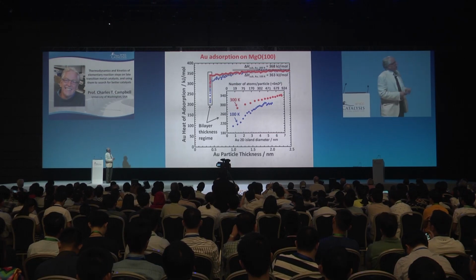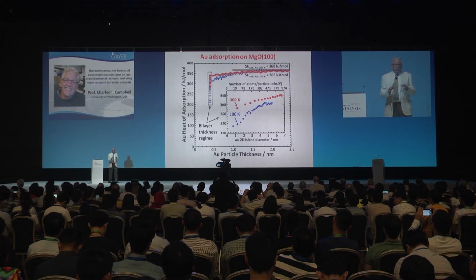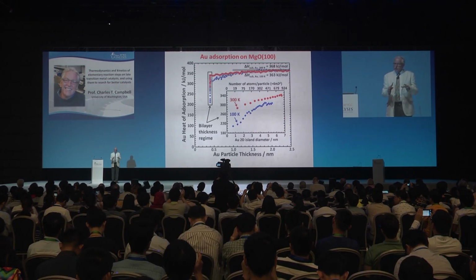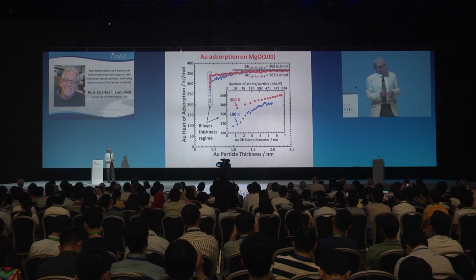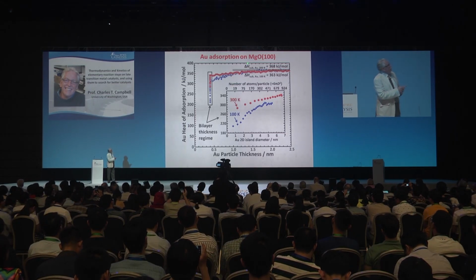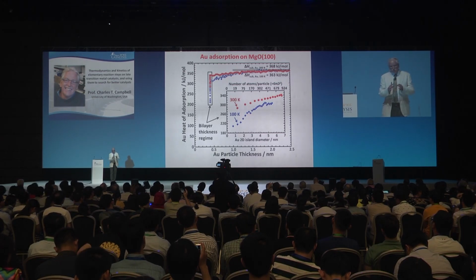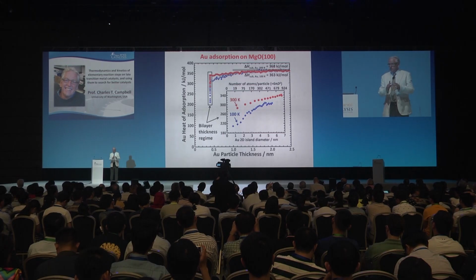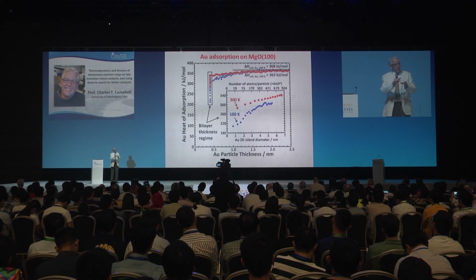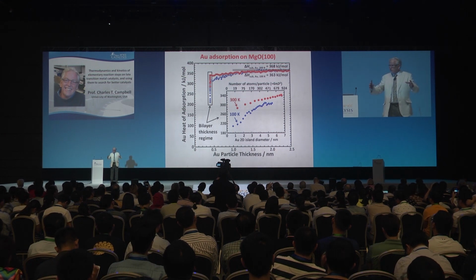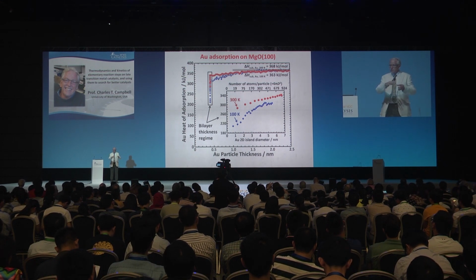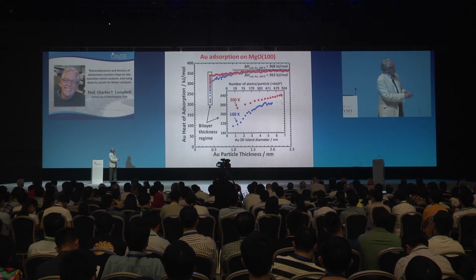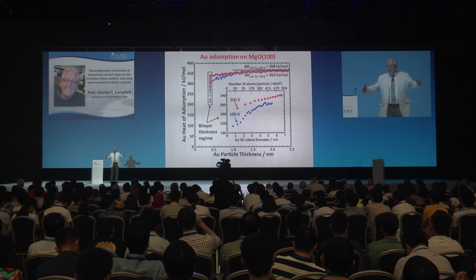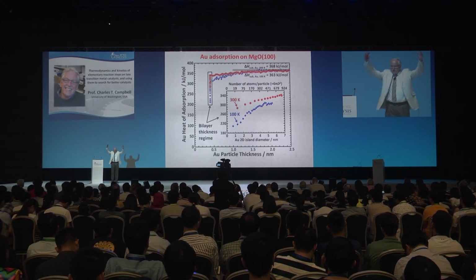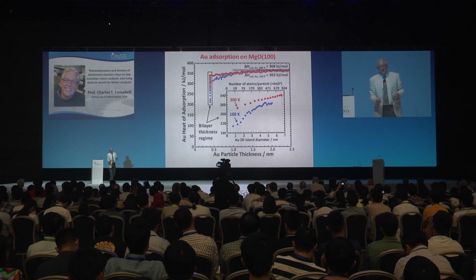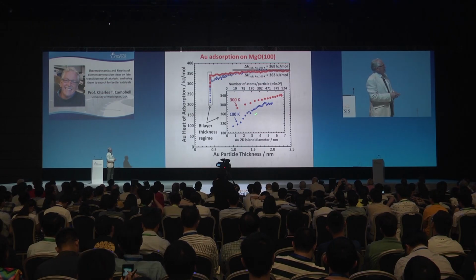Gold adsorption on magnesium oxide is quite different. In most of these systems, the particles grow with something that's approximately hemispherical shape, and you can sort of see that in that STM image from Jim Flege's group. But for gold on MgO, it's a strange growth. It makes bilayer islands to start with. And so that's islands that are 2 atoms of gold thick. And the islands grow in lateral dimension as you add more and more gold to that without getting thicker until they get to about 7 nanometers in diameter. And then the islands stop growing out at all, and they grow straight up after that. It's a strange growth mode. You can understand it from the kinetics of the process, but that's what happens.